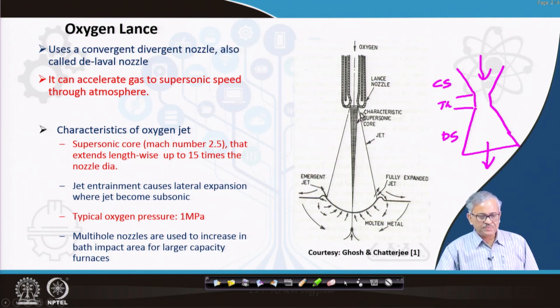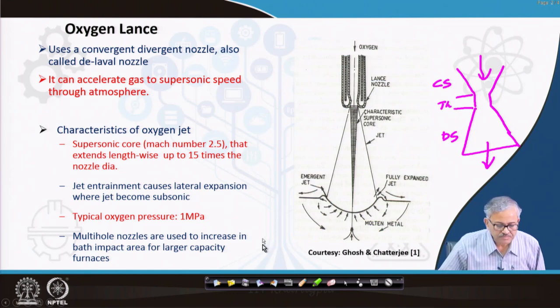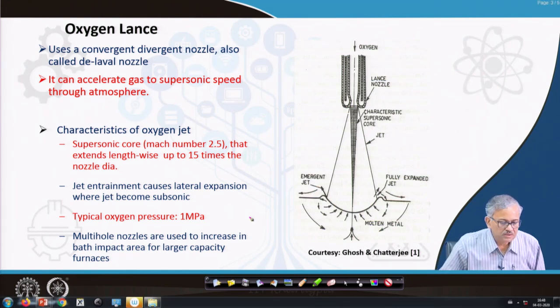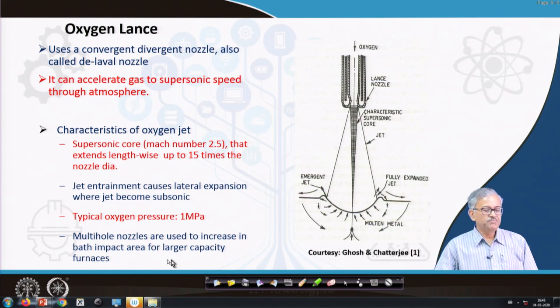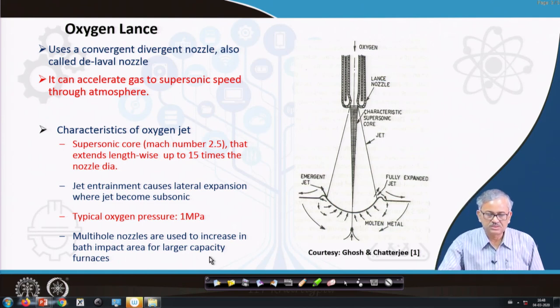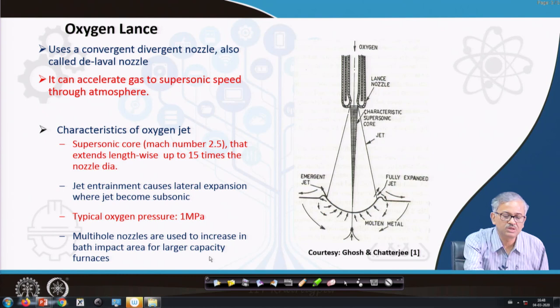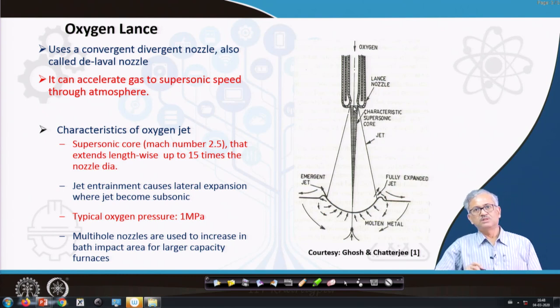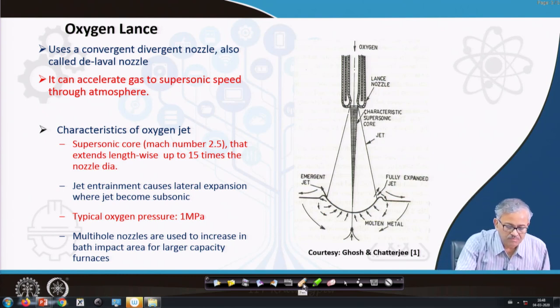And this is about the nozzle. And one thing is that we use multi-hole nozzles, right? We use the multi-hole nozzle to increase the bath impact area for a large capacity furnace. For a large capacity furnace, it is not just one nozzle. You use the multi-hole nozzle. And if I draw the plan view of the nozzle, it will look like this. This is the nozzle, and you have several convergent-divergent nozzles inside.